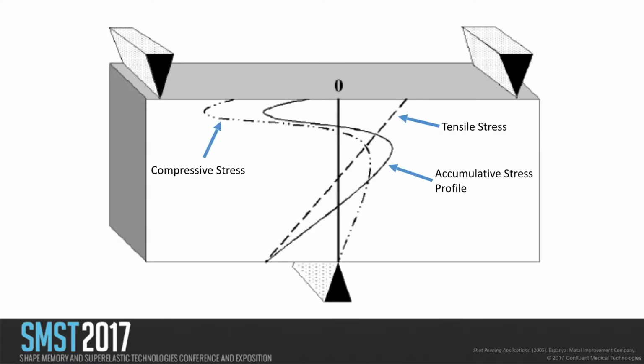And how this works with fatigue is that when I bend this material, what's happening in this image is you are bending the material along this zero axis. The dotted lines represent the compressive stress from shot peening and the tensile stress that you're imparting while bending, and the solid line represents the accumulative total of those stresses. What you'll notice is that this solid line is still in a compressive region at the zero mark where you're bending that material. What that means is that the material at the very outer edge is not in tension. Typically what you see in fatigue failures, particularly in medical devices, is that the surface is in tension, and then if you have a micro crack or any stress riser there, it'll cause that crack to propagate and the substrate to fail.